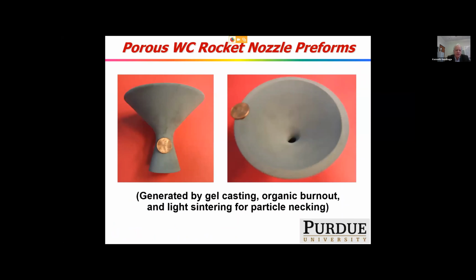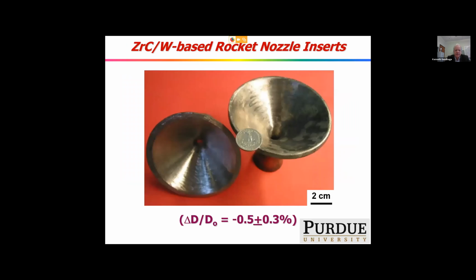So we've also used gel casting. We worked with a company to develop a gel casting process to make a rocket nozzle preform liner. This is a porous tungsten carbide preform after gel casting, burning out the organic and light sintering to make a 50% porous rigid preform. And then we converted that into a rocket nozzle liner using our DCP process. And again, the diameter change here was less than 1%.